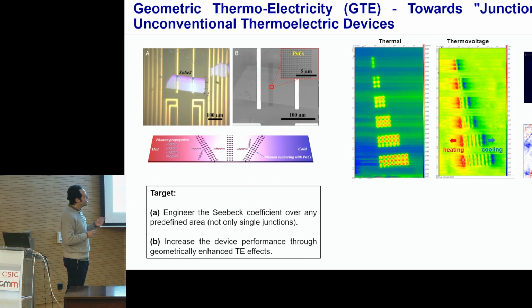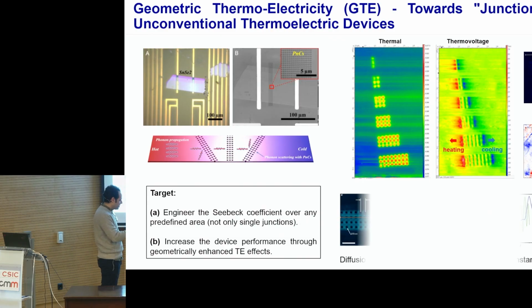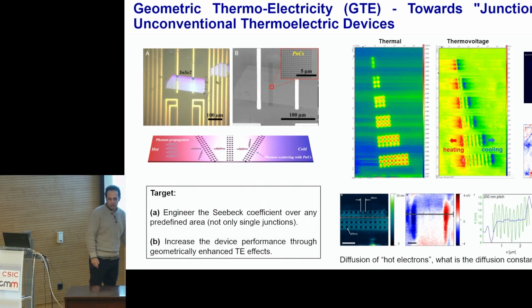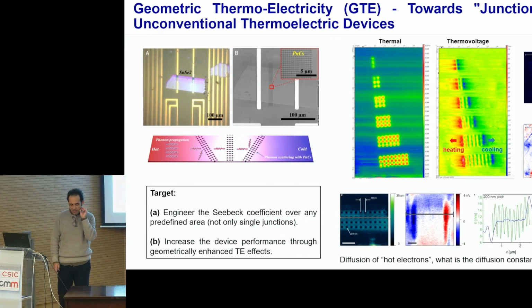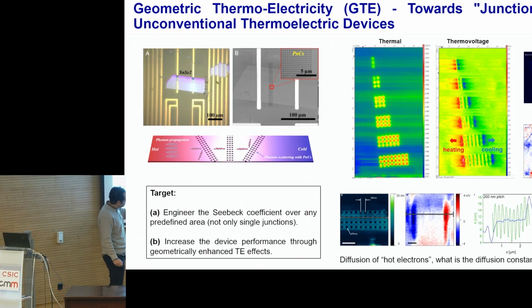Okay, and this is not all. The thermovoltage also accumulates by creating more and more patterns. We accumulate the thermovoltage and we create areas of a completely different Seebeck coefficient, completely different thermovoltage. So as you see here, we found the proper patterning in order to create completely different Seebeck coefficients left and right of the pattern that we create.